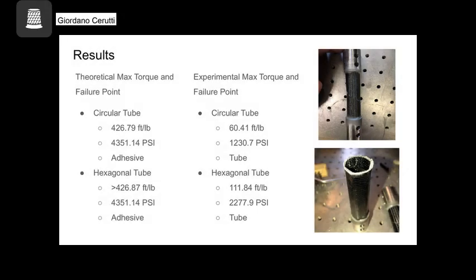For our results, on the left-hand side, you can see our theoretical max torque and failure points of each of the tubes. For the circular tube, it was about 420 foot-pounds. This comes out to a shear stress of about 4,300 psi on the adhesive bond. The failure point for this was the adhesive joint. Yet again, the goal of this was for the adhesive joint to break before the tube.